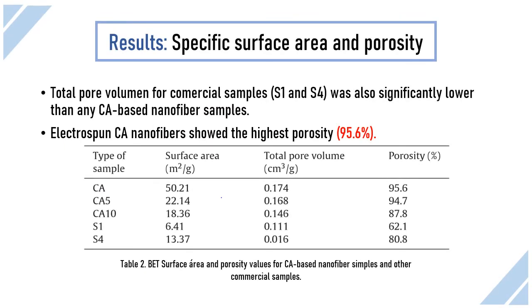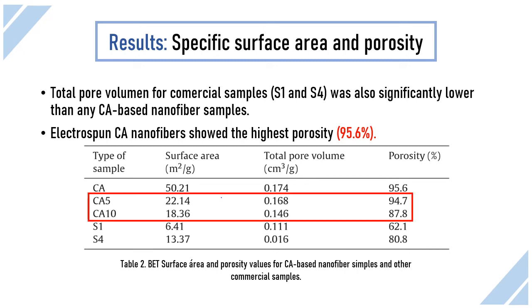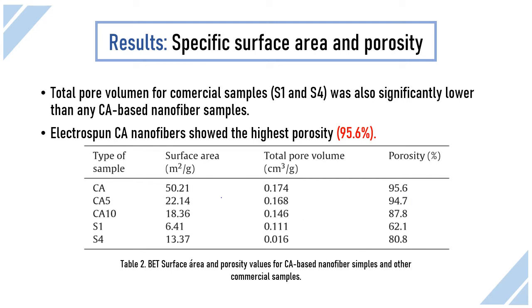The specific surface area and pore size distribution were determined by BET. As we can observe, the decrease in surface area and total volume for CA5 and CA10 samples may be attributed mainly to the increase in fiber diameter and change in morphology from bead-free to beaded fibers. Total pore volume for commercial samples was also significantly lower than any CA-based nanofiber samples. Electrospun CA nanofibers showed the highest porosity of 95.6%.